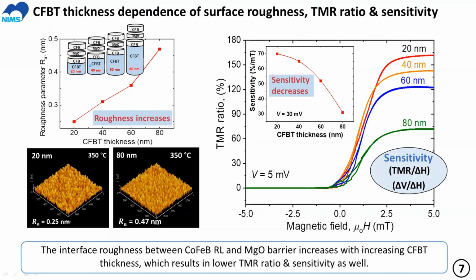We just increased from 20, 40, 60, and 80 nanometer. We were looking forward to increasing the soft magnetic properties of the free layer, but unfortunately, because of increasing this thickness, we found that the roughness of the surface started to increase, and because of this, as you can see here, the TMR ratio decreased, and so the sensor sensitivity started to decrease. So we fixed 20 nanometer CFBT thickness as our superior magnetic free layer.